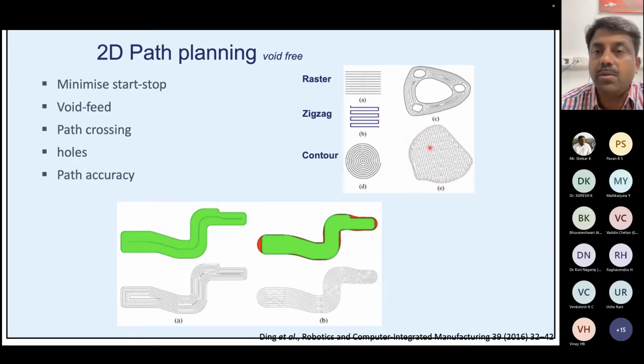So instead of doing that, we can also do what is known as contour path planning. In contour path planning, the layer is created by depositing beads parallel to the outer contour of the object. For example, here we see a layer we have to create. In a contour plan, we start producing this layer by creating the beads parallel to the contour of the surface. And we also follow some strategy. For example, if we start from outside to inside when you produce, you always incur some voids at the middle part, and that is not really recommended. So instead, we first identify the medial axis, the middle axis of this layer, and then start from inside and go outside. Then we end up producing a very nice layer, and this is what is known as MAT, medial axis transformation, followed by contour planning.